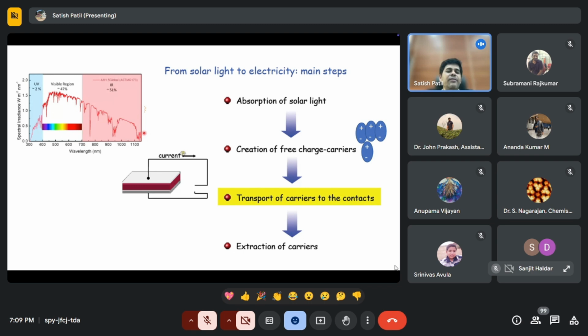You get light in different parts of the spectrum. You get less light in the UV part of the spectrum, approximately less than 2%, because these are high energy photons. You do not want a large portion of this light hitting the planet, because it can penetrate your skin and cause a skin burn. You often see an argument about ozone depletion. Ozone depletion allows more UV light to penetrate towards the planet, but as it passes through the atmosphere, this UV light is absorbed mostly by ozone. So you don't get a large number of photons in this range.